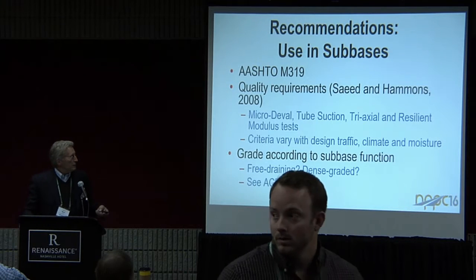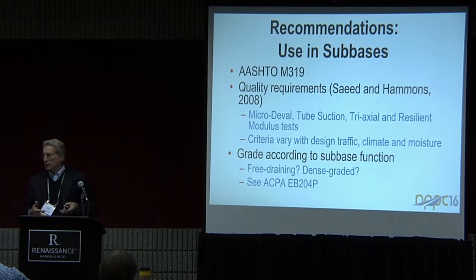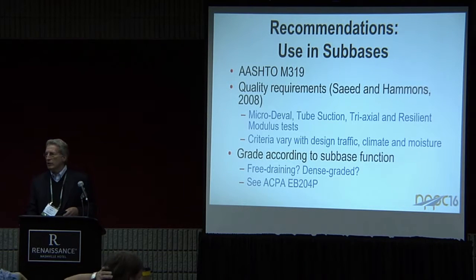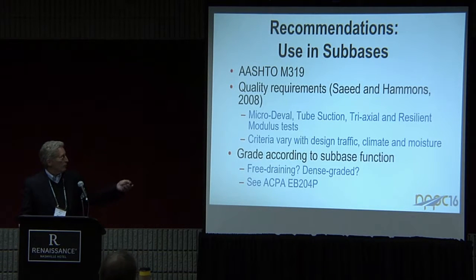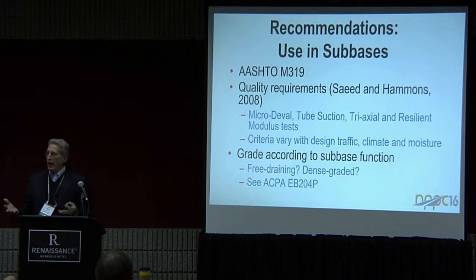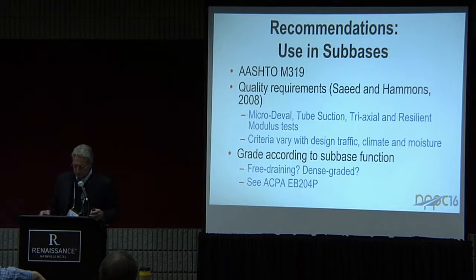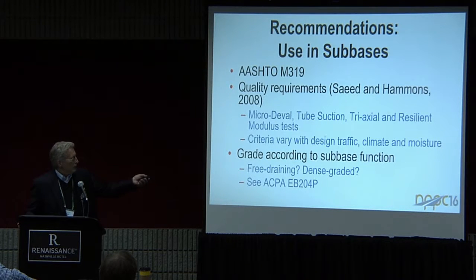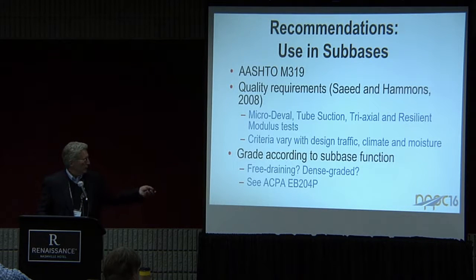And again, for lower functioning applications such as farm to market roads or county roads, where it's really not a critical application, the requirements for all of these are much less restrictive than if you have a high type pavement like an urban interstate pavement. And of course, crushed concrete can be graded just as you grade normal aggregate according to the needs for the subbase function, whether it's going to be a free draining material or a densely graded material. There is an American Concrete Pavement Association engineering bulletin. It's all about subbases, and it addresses the requirements for free draining and dense graded crushed concrete aggregate. So I would direct you to contact your local ACPA representatives for copies of that publication.